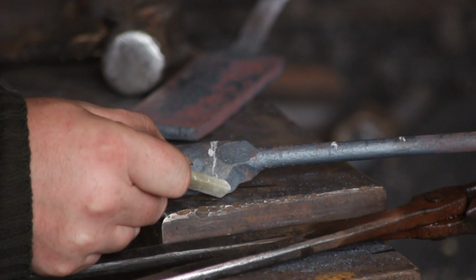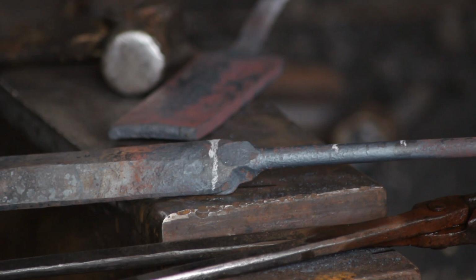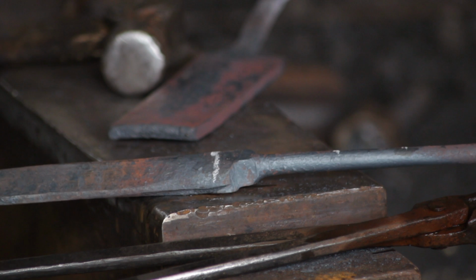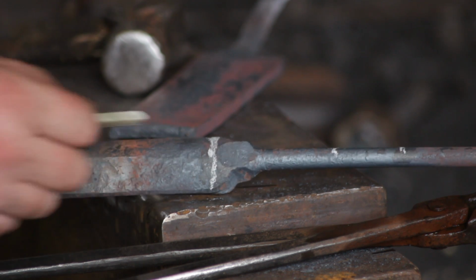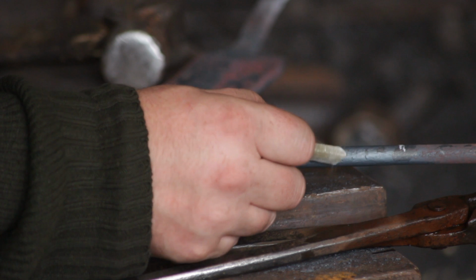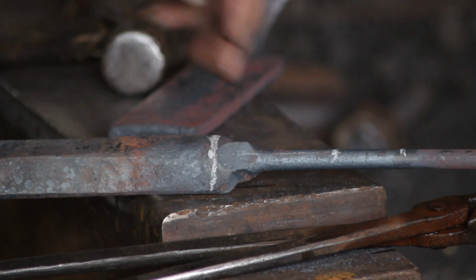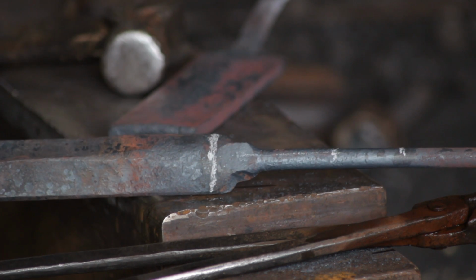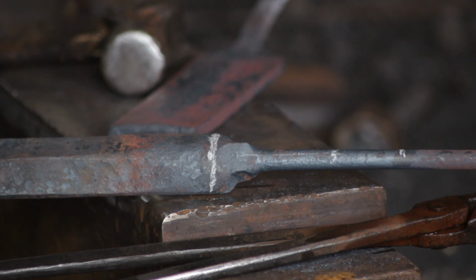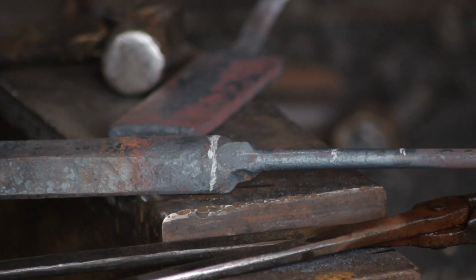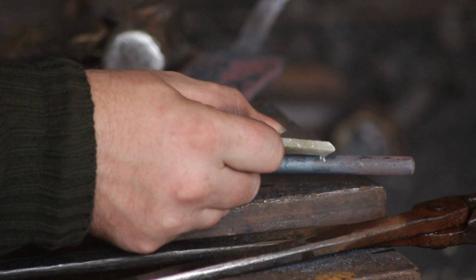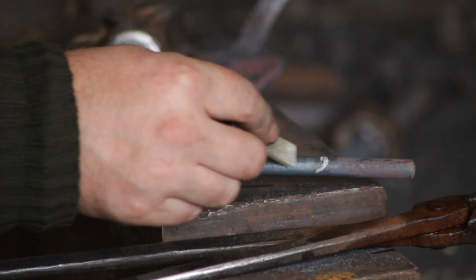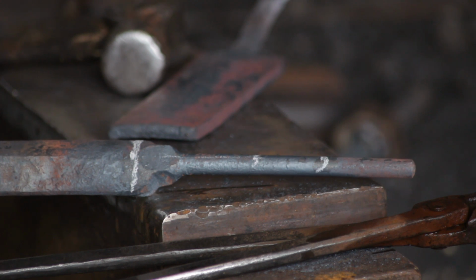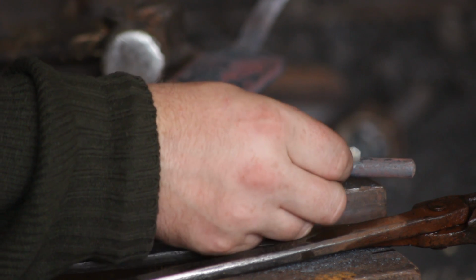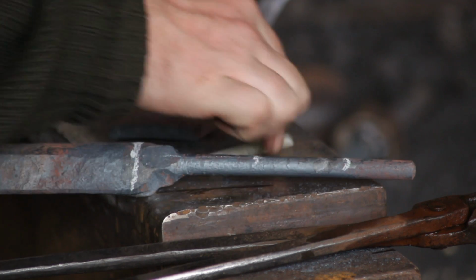So once that's done and the blade is cooled down, I will mark off where the blade tang transition will be, so that'll be where that rounded collar is. And I've gone a little bit far back, and that's just to ensure that I have the right volume of material there for the collar. And I need the tang beyond that to be 2 1/4 inches long in order to get all the curves in there. So that marked that second point, and then I will add 1.5 inches to be upset, and that will allow me to create the scarf. And in fact I decided to add an extra 1/2 inch to that, so 2 inches, in order to upset that end.